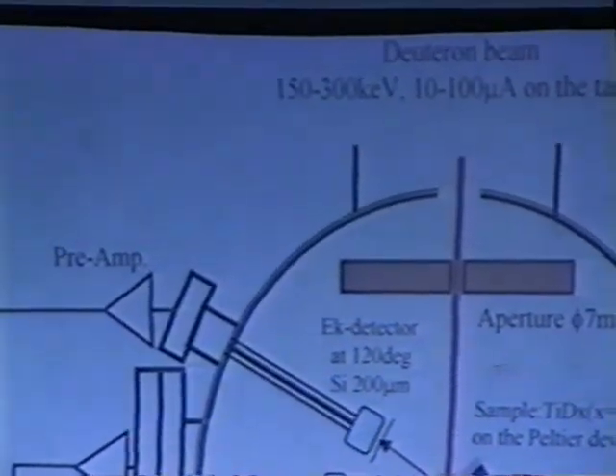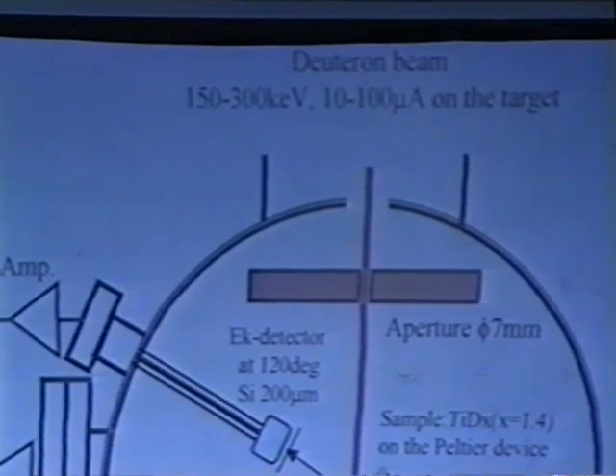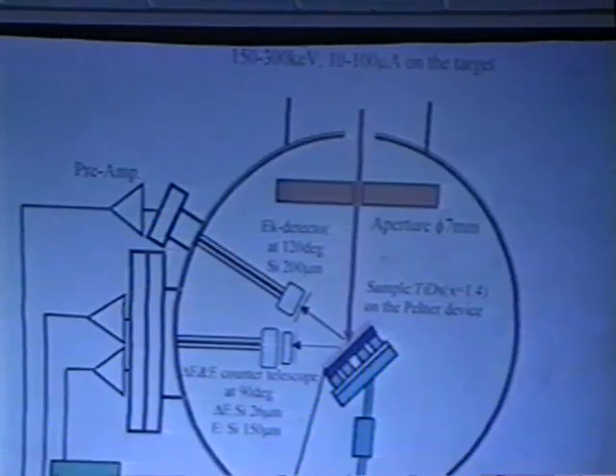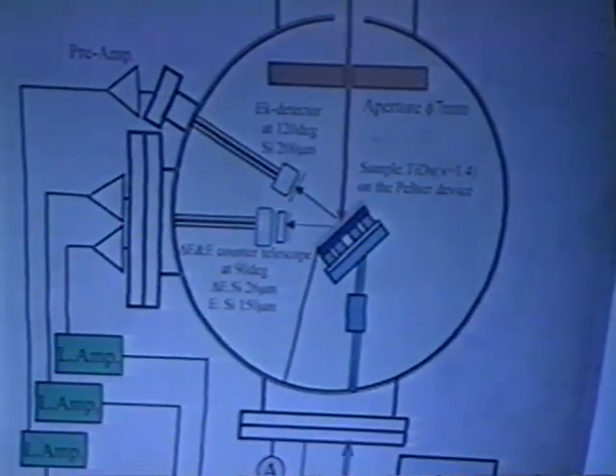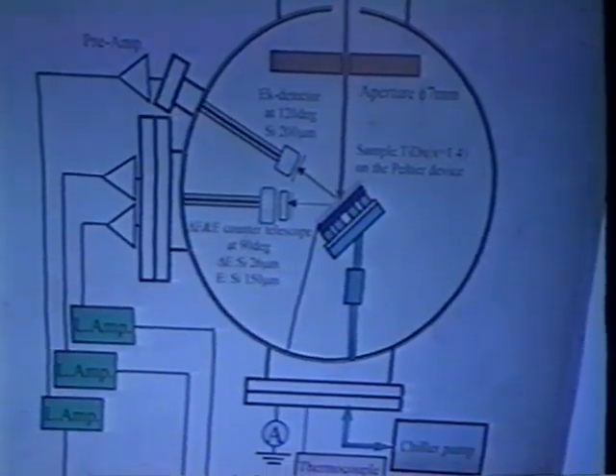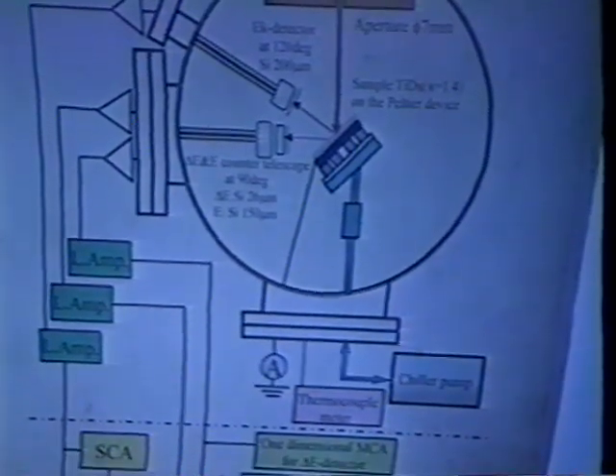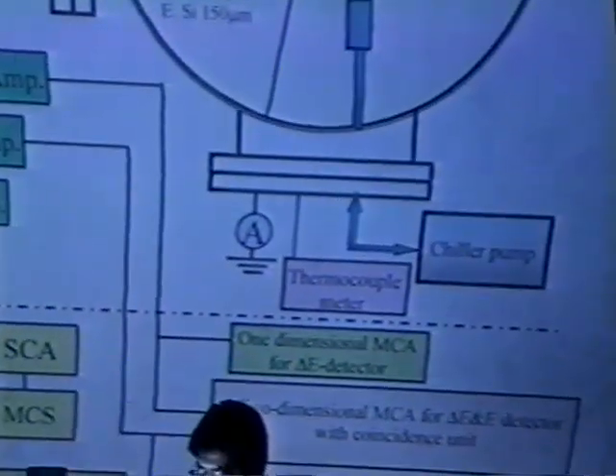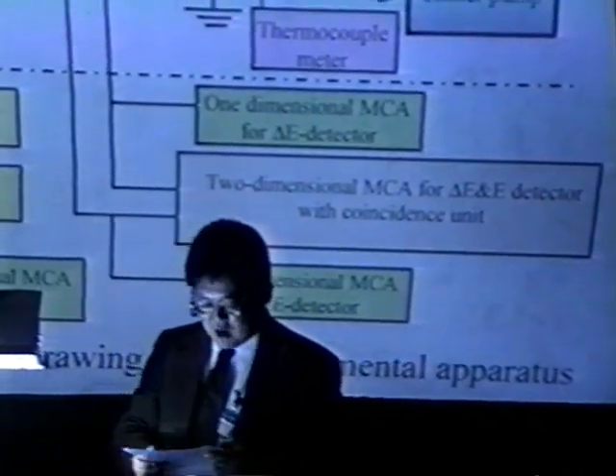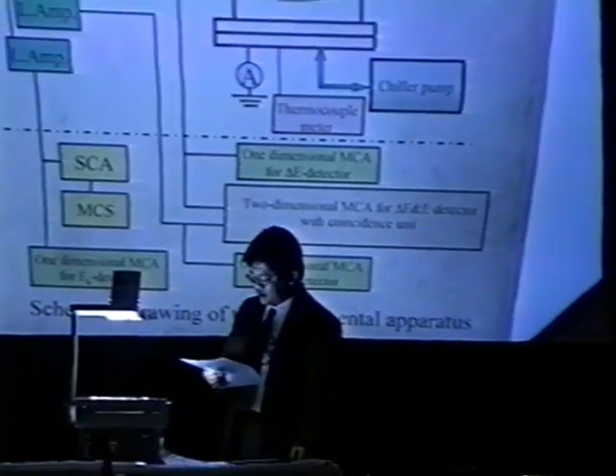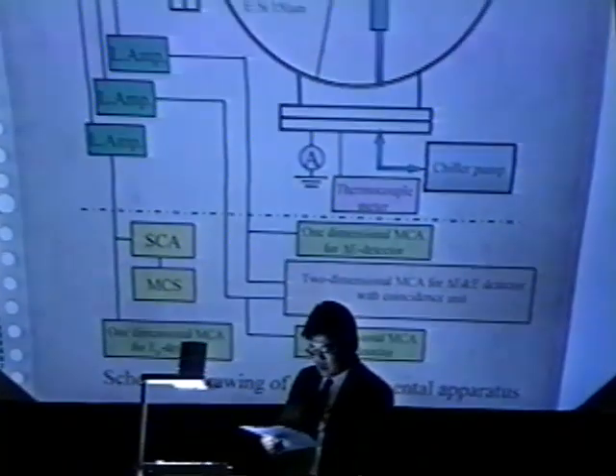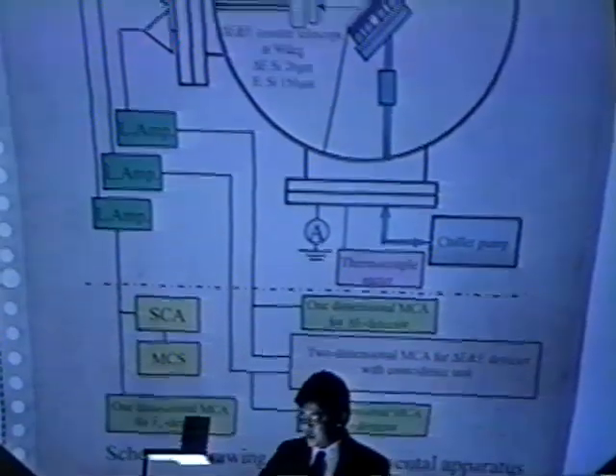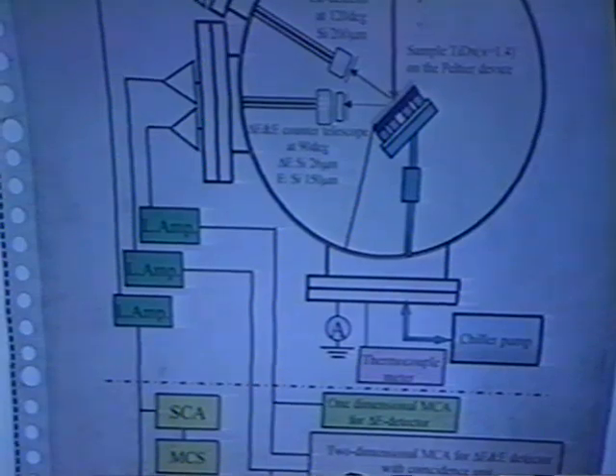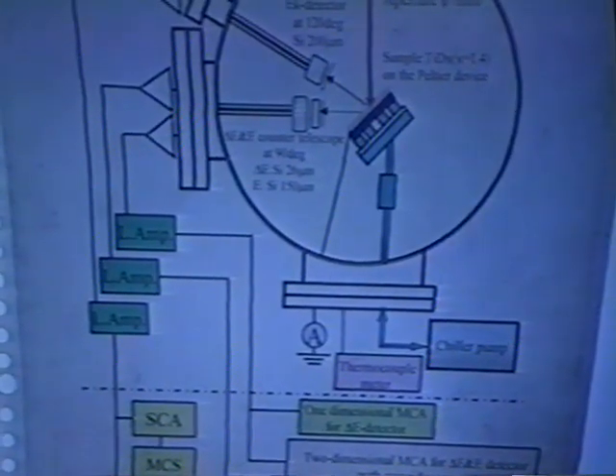This figure shows a schematic drawing of the experimental apparatus. We have used a highly pure TiDx plate sample, and the sample was mounted on the Peltier device for cooling. During the beam run, the beam current was about 30 microamperes, and the temperature of the sample was from 5 to 15 centigrade. We have used charged particle spectroscopy with silicon delta E and E detectors. Also, we have used a simple silicon detector. Of course, we set up aluminum foils in front of these detectors to reject scattered neutrons.